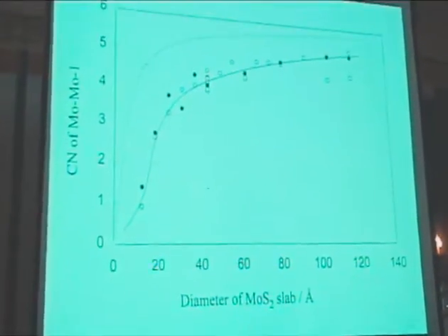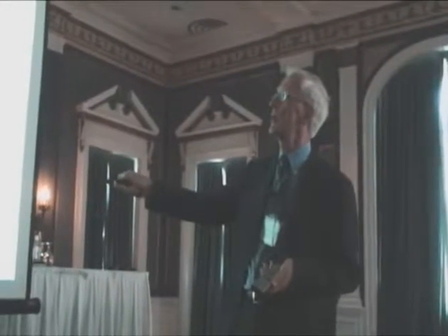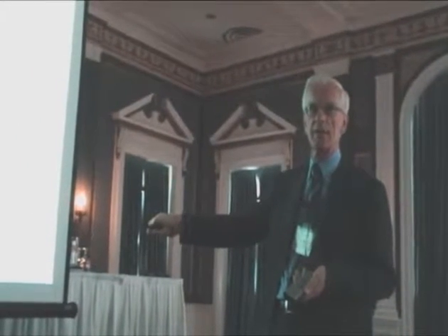Now, allowing for distortion at the edge, when we make this into a new model, we can come up with a new line. And now you see that when my coordination number would be 4, I am here, and now I am close to 35. And then I'm in good agreement with electron microscopy. So the electron microscopy was right. The mistake was in the EXAFS theory. And the mistake in the EXAFS theory was assuming that all distances are equal and are just having a Gaussian distribution.